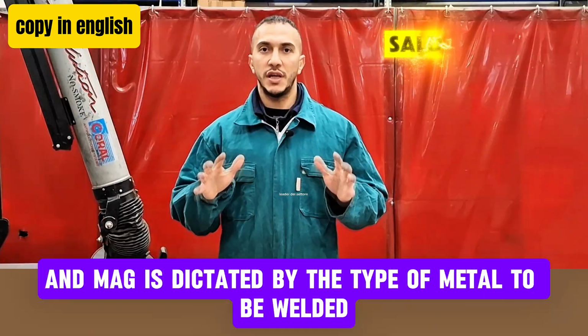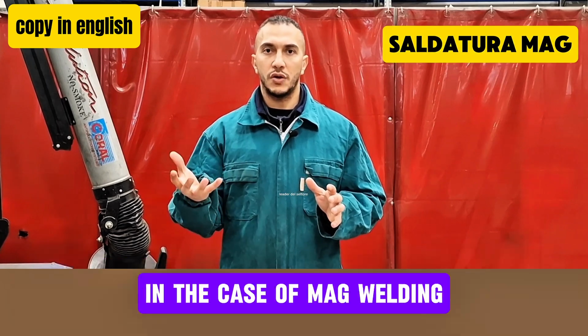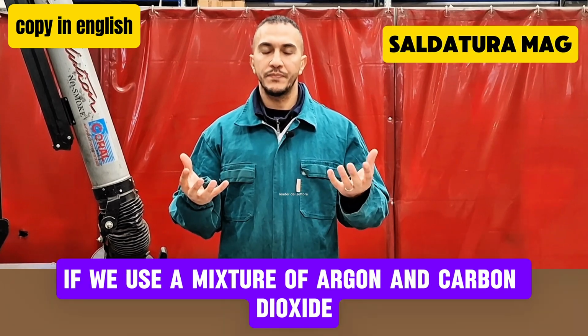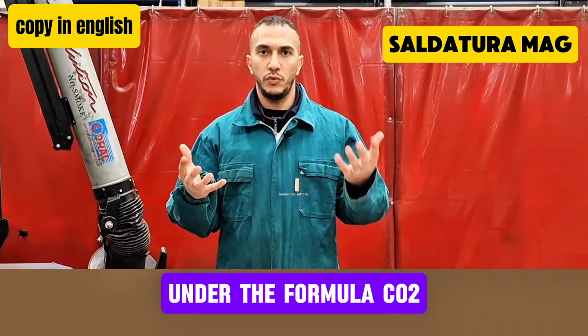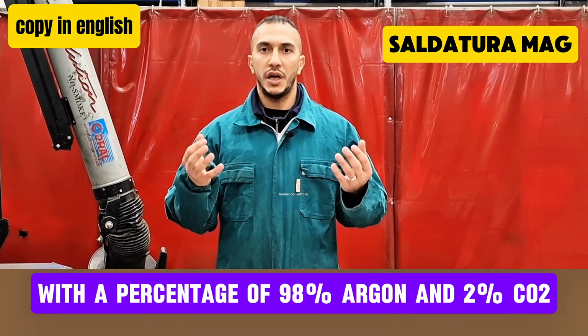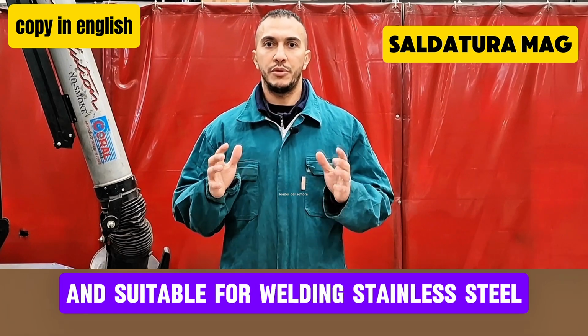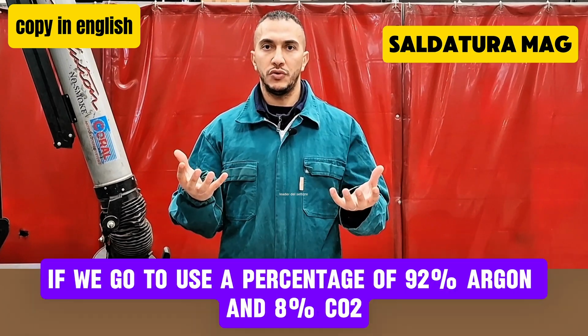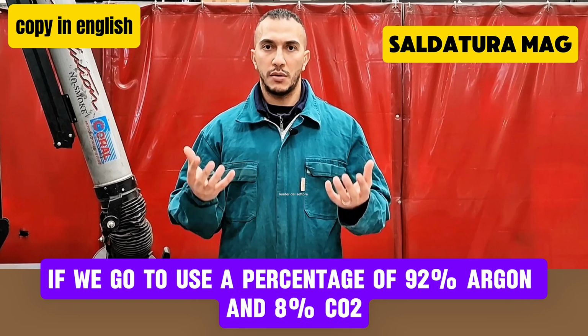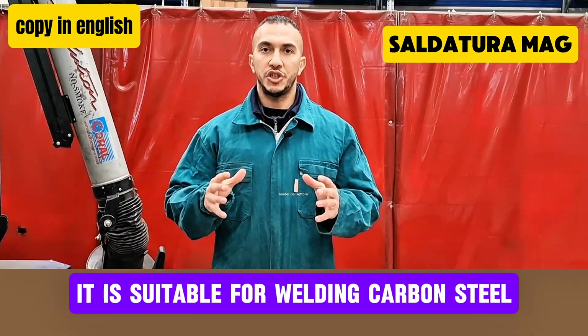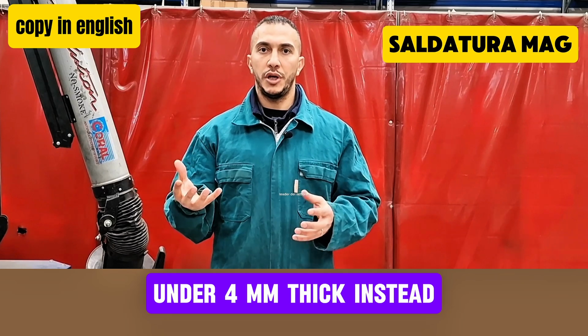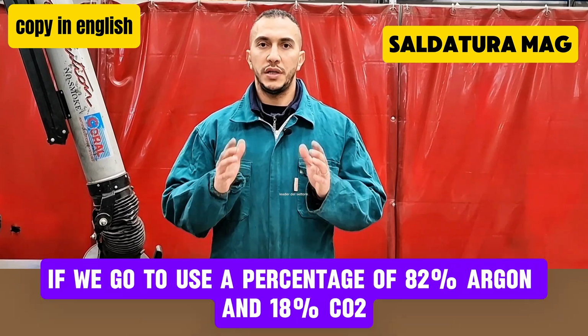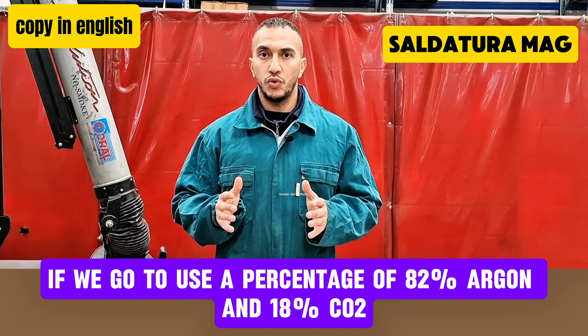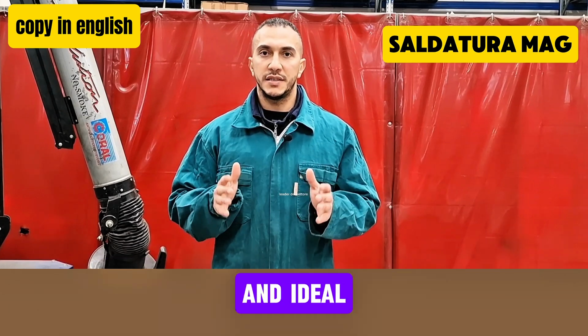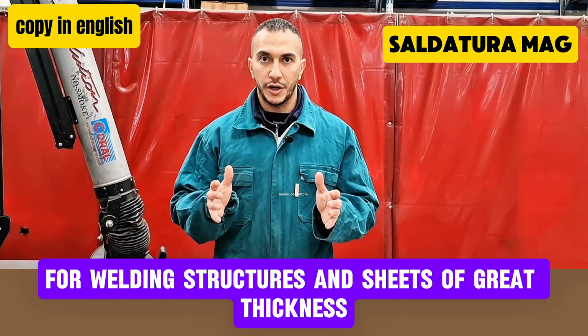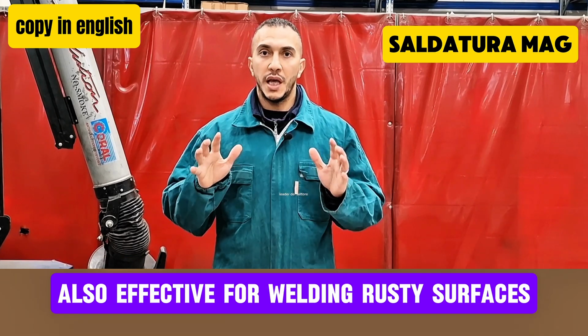The choice between MIG and MAG is dictated by the type of metal to be welded. In the case of MAG welding, if we use a mixture of argon and carbon dioxide (CO2) with a percentage of 98% argon and 2% CO2, it is suitable for welding stainless steel. If we use 92% argon and 8% CO2, it is suitable for welding carbon steel under 4 mm thick. If we use 82% argon and 18% CO2, it is suitable for welding carbon steel and ideal for welding structures and sheets of great thickness, also effective for welding rusty, even dirty surfaces, always for MAG welding.